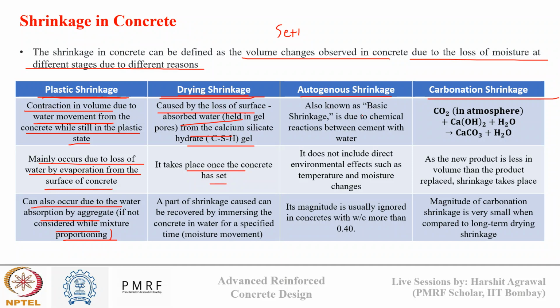Then autogenous shrinkage, which is known as basic shrinkage also, is something that will occur. We can't stop it. It is due to the chemical reaction between cement and water. When cement and water react, there is a slight reduction in volume. So the volume of the individual components, cement and water, is more than the volume of the cement paste that is formed. And this is what is known as autogenous shrinkage. It does not include any environmental effects such as temperature and moisture, and its magnitude is usually ignored when the W/C ratio is more than 0.4. So this type of shrinkage is present in a very small amount, but it is bound to occur.